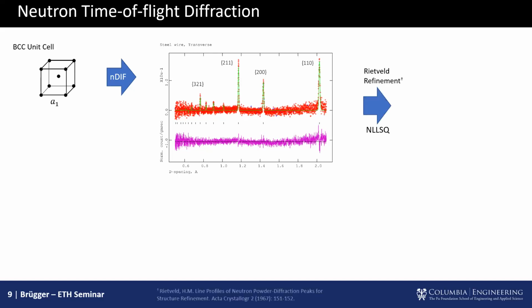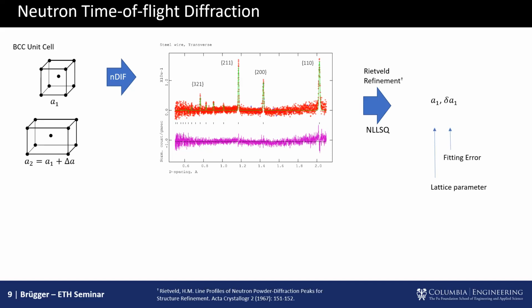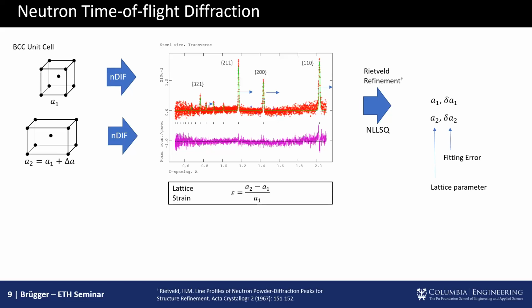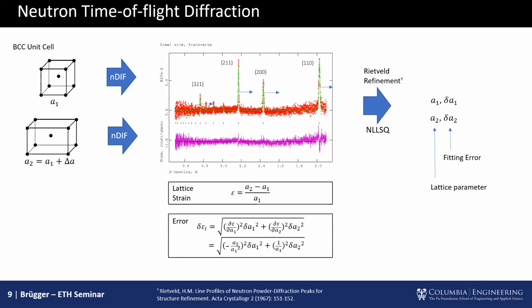So effectively, if we just do a nonlinear least squares fit of that, called Rietveld refinement, we get a lattice spacing. Now we can take that same material with those unit cells and deform it and irradiate the same point again, and then essentially get a second lattice spacing. And from that, we can get lattice strain. So that's essentially the method of traditional neutron diffraction. And this is the bread and butter of what neutron scattering people do, especially in the engineering world. Of course, we can also get an error. So this is fun. This has been done now for 30 years.